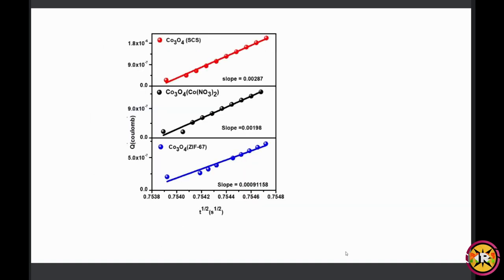So now, coming to the ECSA, the electrochemical active surface area, I have observed from BET that Co3O4 SCS has a higher surface area than the other two. Now I have calculated, when I have done the CV, how much active area is showing. When I calculated this, I observed that the Co3O4 SCS ECSA is also higher than the other two.